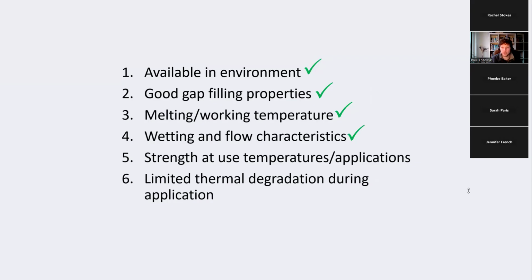Resin, on the other hand, is very tacky at low temperatures, which makes manipulating it and applying it very difficult. Point 5 also goes to birch bark tar. It's basically got better performance. It's stronger across the uses and temperature ranges. And point 6, also taken by birch bark tar, it shows very little change after prolonged exposure to high temperatures.